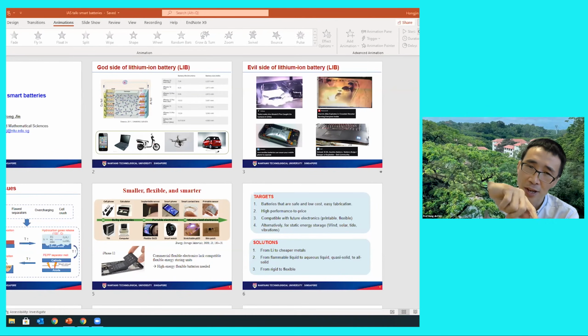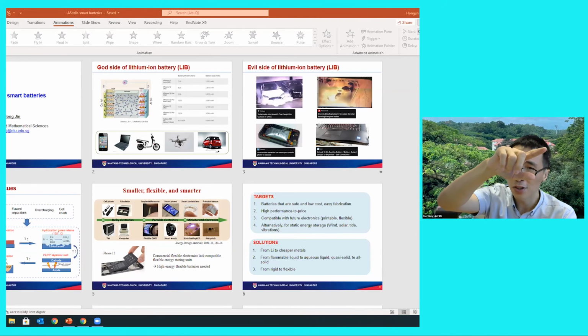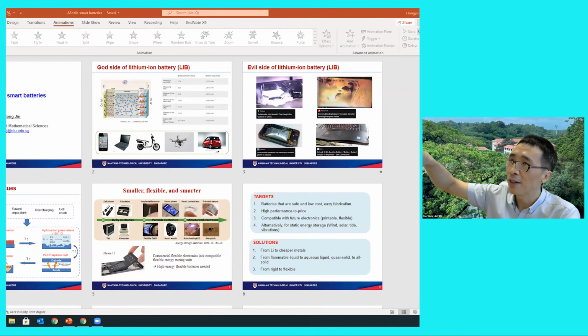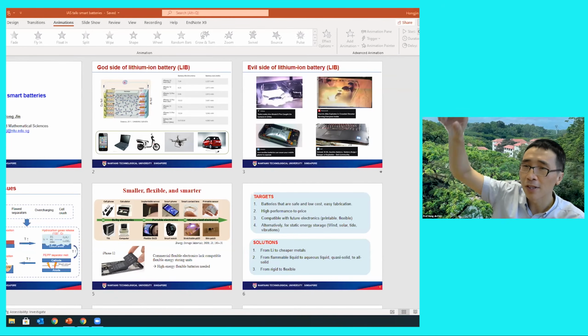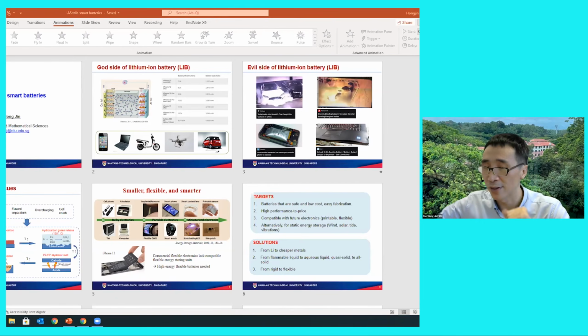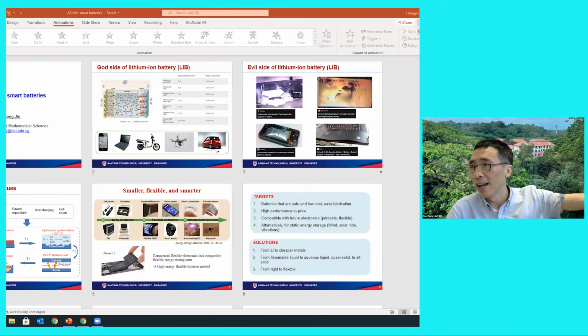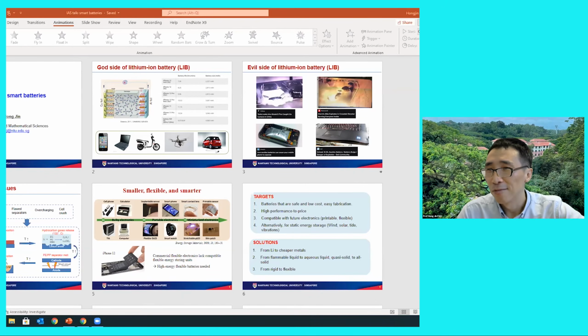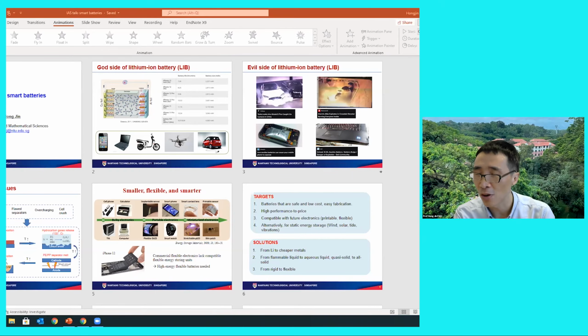But then after a certain stage, the voltage, because in the first charge the voltage increases, and at a certain stage the voltage keeps constant. And after, let's say, 60, 65, 70% charging, the voltage goes up, and the current will be different at a different stage. So if you leave a battery on a lousy charger without the CE certificates, you may cause hazard. You may cause overcharging. If the battery inside does not contain those protection circuits, it may cause hazard.